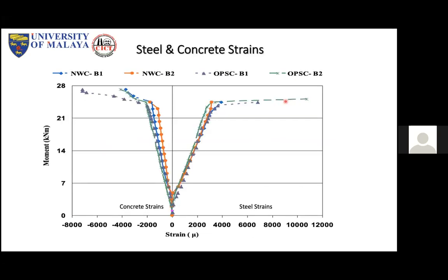That's why you see the strain also, instead of the normal weight concrete, only 2,000 to 3,000 micro strain. But here we managed to get 8,000 to 10,000 micro strain. That means the yielding of steel continues because of the bond between the aggregates, the concrete and the steel, and also the elongation property because of the ductility of the beam. The steel still elongates because the strain is quite high. Even the concrete strain, you can see it's quite high in the beam.